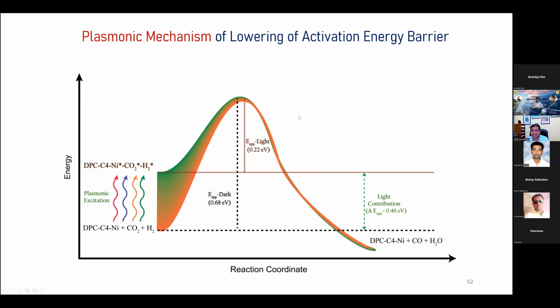We also calculated the activation energy barrier. In the dark, the activation energy barrier is 0.68 eV, whereas in light, it is 0.22 eV. You see a dramatic decrease in the activation energy barrier, and that's why this reaction is happening at a very low temperature, ideally at room temperature.